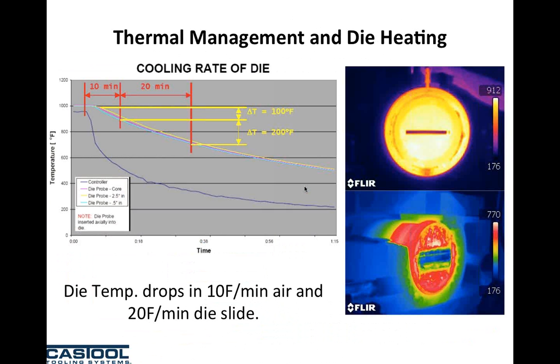You also want to be recording these times. You want to record when the die goes into your die oven, when the die comes out of the die oven, and when the die is used. If you have a 3 to 5 minute delay because you have a butt stuck on your butt knocker, or you're cleaning aluminum from the liner seal face, in 3 minutes your die is going to lose 60 degrees. In 5 minutes it's going to lose 100 degrees.